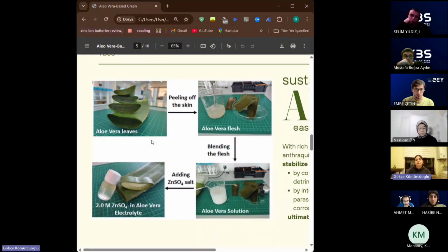The experimental part is getting the gel part of the aloe vera and mixing it with zinc sulfate salt for a 2 molar solution. And we are using it in Swagelok cells, which, if you know, consist of 2 steel attachments, and we are making a symmetrical cell: zinc, separator and electrolyte, also zinc. This is the experimental method, I can say.